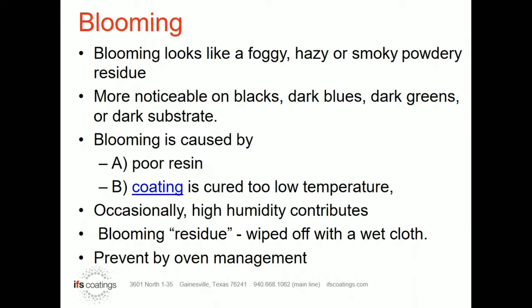So with all that said, usually blooming will wipe off with a wet cloth, or sometimes even a soft dry cloth, it'll wipe off. There are times when it gets that powdery look that you might not be able to get it off, but almost always it's a temperature related cheap resin issue.